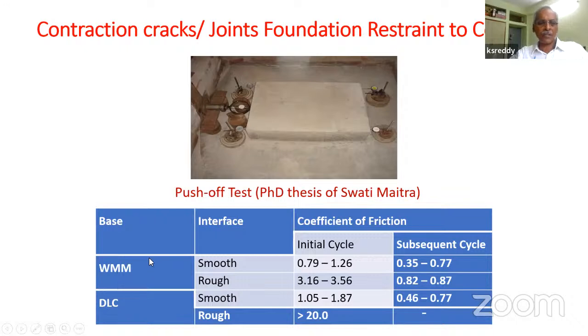When you place the concrete slab on a wet mix macadam aggregate layer, this is the average value of friction that is mobilized: 0.35 to 0.77 when it is placed on a smooth interface with a plastic sheet. And without a plastic sheet, the range of values was 0.82 to 0.87. You can see the difference when you have a plastic sheet. A plastic sheet doesn't make it absolutely smooth. It would still have a significant amount of friction, but compared to a rough interface without a plastic sheet, the friction is significantly reduced. Whereas when you place concrete over DLC with a plastic sheet, the range was 0.46 to 0.77. And over a rough interface without a plastic sheet, we could not actually measure it. The screw jacks were not adequate to actually push the slab because the friction was as large as 20.